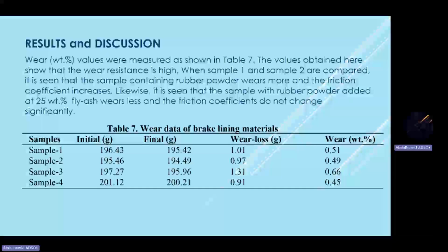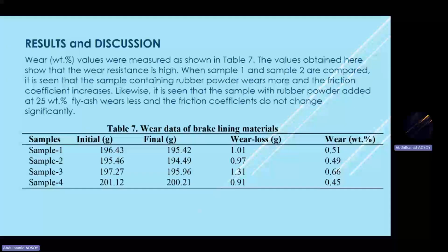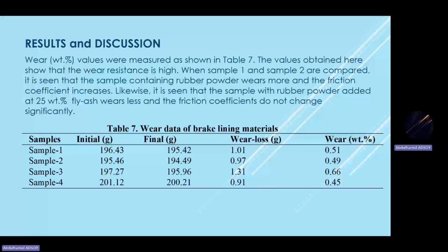Also, during the tribological test, one of the important properties is the wear properties of the brake materials. Values were also measured, and we can see them in table 7. Now, we can see that the wear resistance of the materials is very high. They have 0.5 to 4% by weight wear, which is very high.